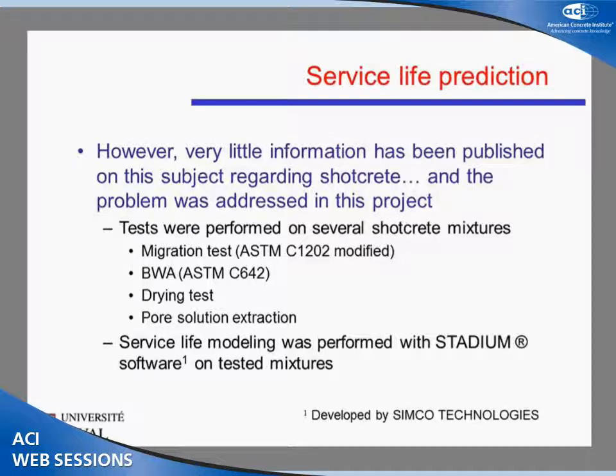Now, as I said before, very little information is available for Shotcrete specifically. So what we did in our case, we performed several tests that are required as inputs for service life prediction. And I'm talking here about a migration test, which is a modified version of ASTM C1202, the regular boiled water absorption test, an in-house drying test, and we made an analysis of the pore solution of the mixture tested. With these results, we were able to use these inputs in a service life prediction software called Stadium.